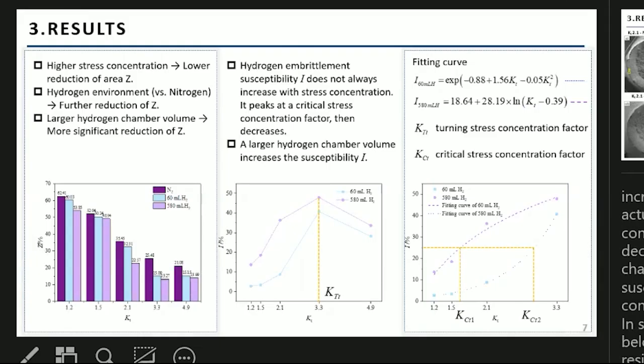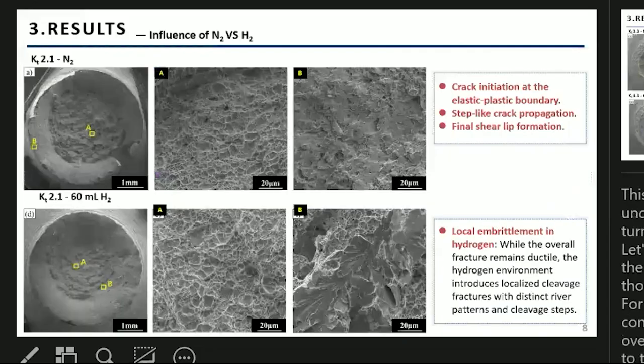In smooth specimens, an index below 25% may define hydrogen resistance. This implies a threshold may exist below which stress concentration has negligible impact to defects. However, test conditions, such as chamber volume here, change the curve, and the associated critical stress concentration factor changes. So it's important to establish standards for environment and experiment and engineering if we need further application. And this section is helpful for understanding the concept of turning stress concentration factor.